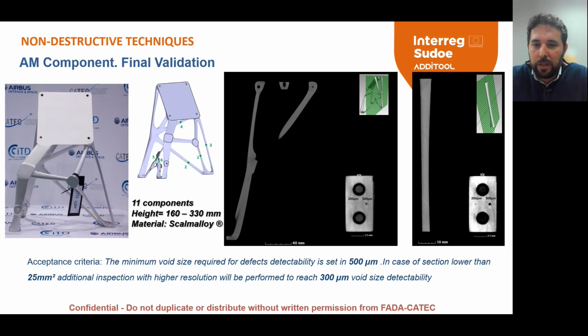Let's put an example. This is a Scalmalloy bracket manufactured by Laser Powder Bed Fusion. It is a flight component, and it is installed in the JUICE satellite, which will travel to the Jupiter icy moon. It's part of the secondary structure, and the acceptance criteria was set in 500 microns. And in case of section lower than 25 square millimeters, the acceptance criteria was set on 300 microns.